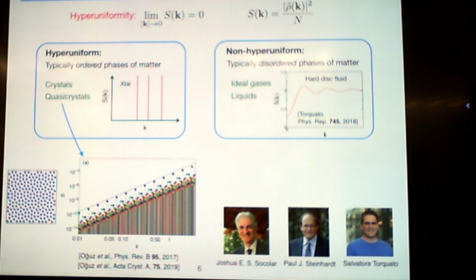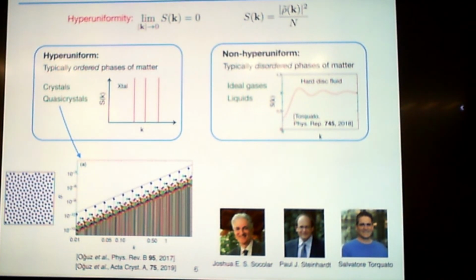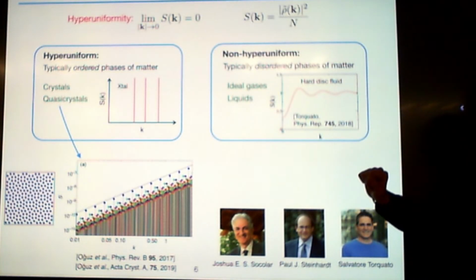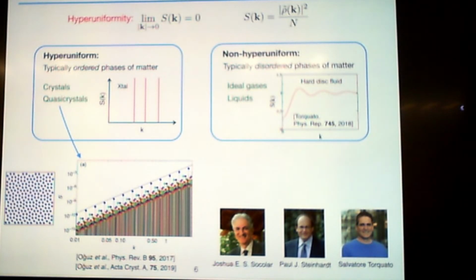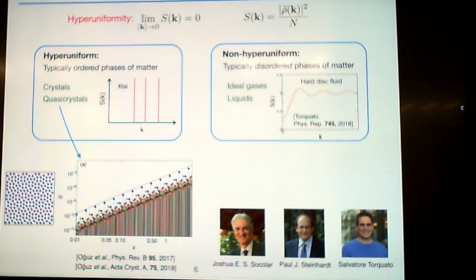So that's the hyperuniformity concept. Hyperuniformity means basically whenever you have long-range order in the system, can be translational symmetric order, can be also rotational symmetric order, can be any type of order, then the structure factor, the system is going to be hyperuniform. Whereas, on the contrary, if you have non-ordered, disordered systems, phases or states of matter, such as liquids, or ideal gas, or gases, or glasses, for that matter, typically structure factor does not go to 0.